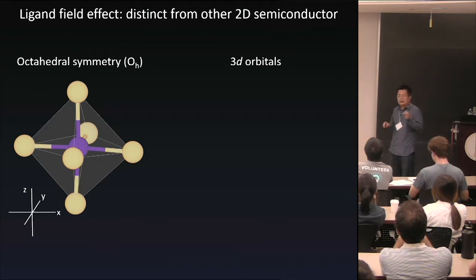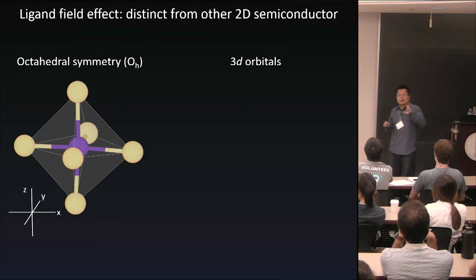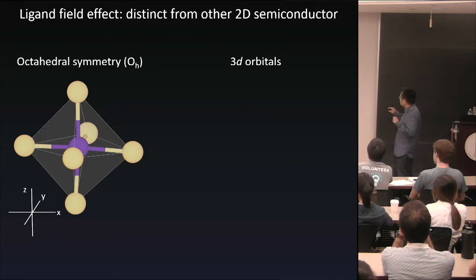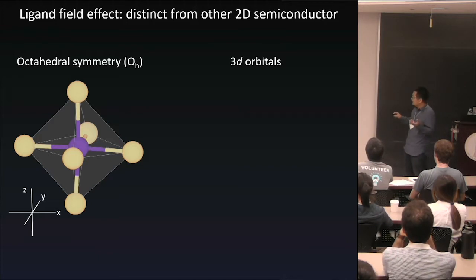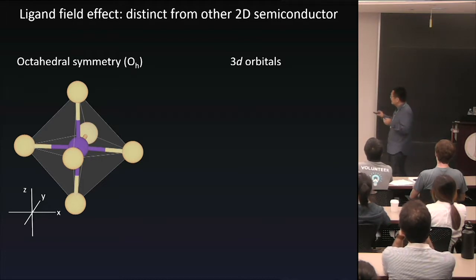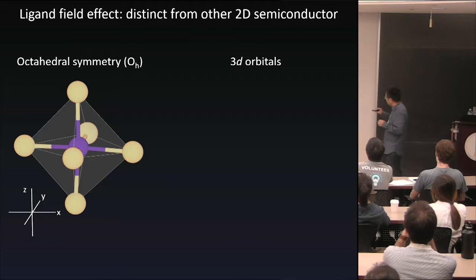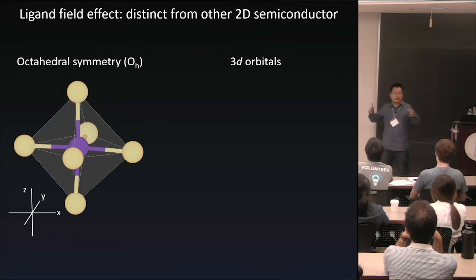So the other is what happens in this chromium atom, which has 3D ions. Therefore, we actually measure a D to D transition, which is symmetry forbidden, because there's no change of angular momentum, right? But the reason we can see it is the crystal itself. If you look at the unit cells, it's a chromium atom in the center with 6 iodine on the corner. It's an octahedral edge-sharing structure.